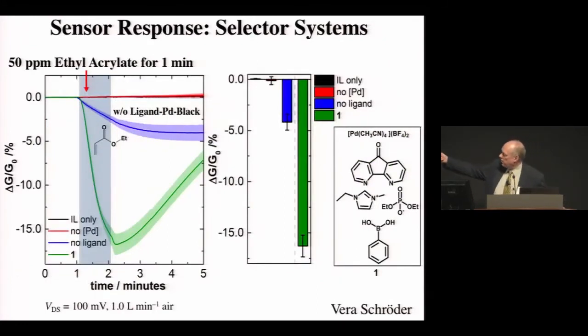So what we have here now is a decrease in conductivity. I'm plotting it the opposite way from when I've shown it before, but that's the way Vera wanted to do it. Without the palladium or without other things, we get really no response. If we throw the palladium in there and we leave out this ligand, we get a response and it's completely irreversible, because the palladium-0 is not stable under those circumstances, and it just makes colloidal metal that sticks to the nanotubes, and this is what you get. So all the palladium got taken out.